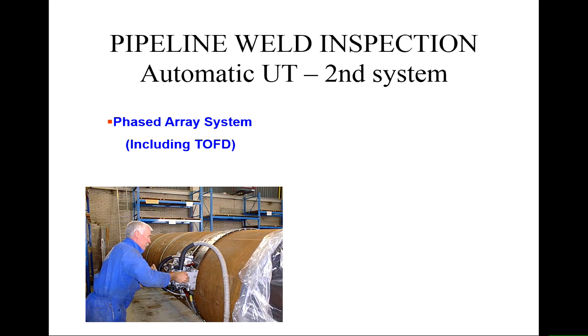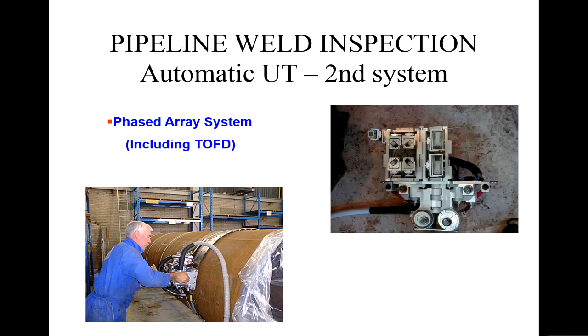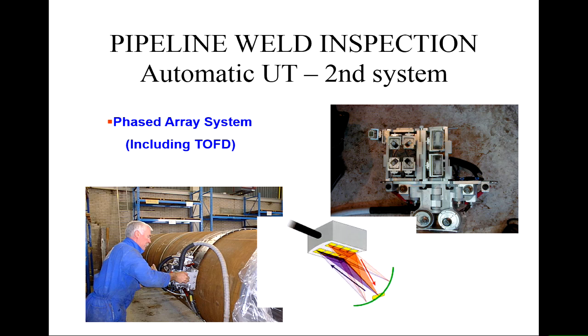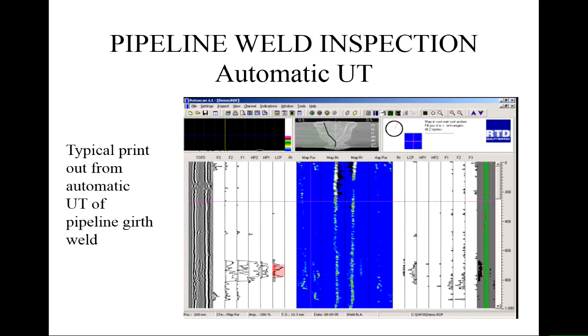You can see there's a track and there's a detector, and that detector is crawling its way around the track. So in theory, the detector is simpler, but the processing is quite a lot more complex. And that's the picture that we had before. And now you're seeing these arrays here, and you're looking at the different reflections coming back, and then the phase differences that you would expect from the detector here and the detector here to give you the positioning. So depending on which detectors have signals arising, you can see which phase difference, and that tells you which angle it was at, and then where the defect actually is.